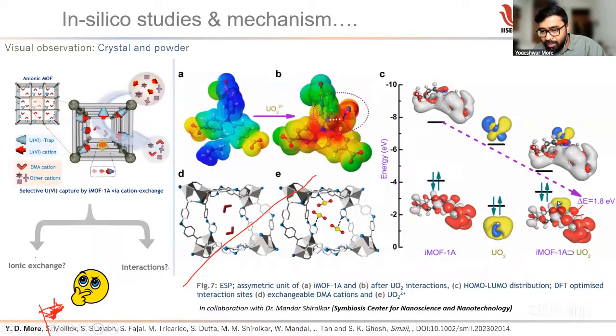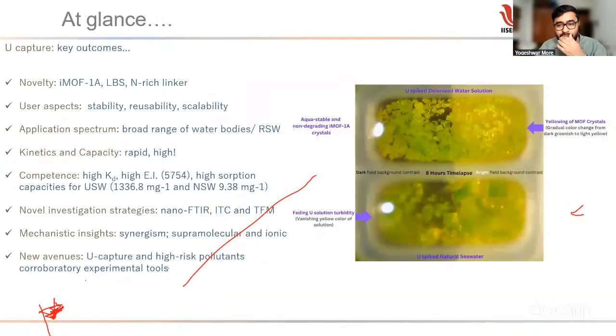And here it is, you can see the MOF HOMO is stable. HOMO and LUMO are highly stabilized in the case of the uranium and nitrogen interaction in the given DFT-optimized interaction site, and this is due to the exchangeable DMA cations and the Lewis basic sites, called the nitrogens. So overall, this is the picture basically, and with that, what we observe then.